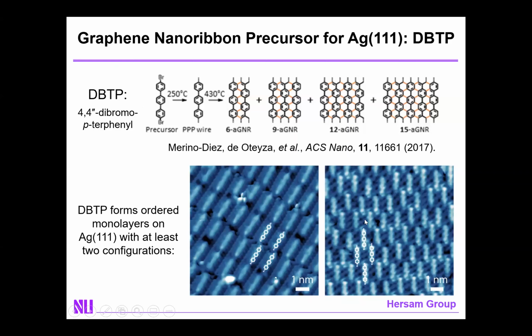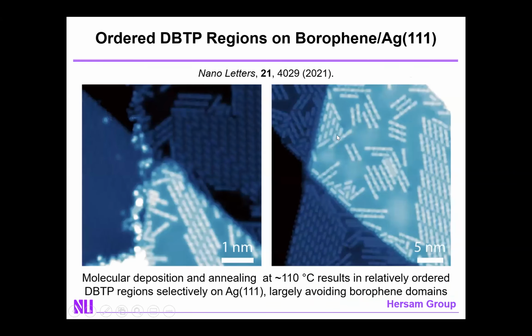Perhaps more interestingly, if you deposit DBTP onto a submonolayer coverage of borophene on silver 111, you find that the molecules adsorb selectively on the silver. And at relatively modest annealing conditions of about 110 degrees C, you find that these molecules form relatively ordered structures, but are avoiding the borophene, which then suggests that if we go to higher temperatures to convert these into graphene nanoribbons, we would have a graphene nanoribbon-borophene heterointerface forming spontaneously via the molecular self-assembly. And that is indeed the case.